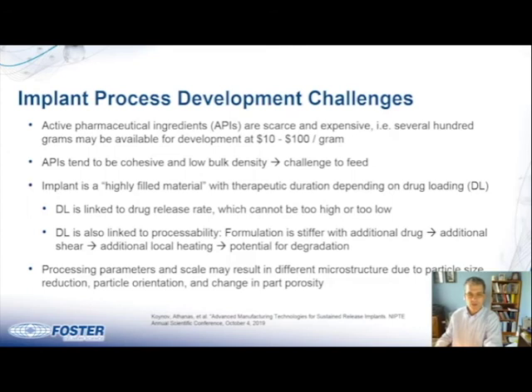The processing parameters and scale may result in different microstructure due to particle size reduction, particle orientation, and change in part porosity. These are all things that happen in both the single and the twin screw process. As I mentioned, twin screws are excellent mixers, and they do so by imparting shear onto the formulation, and that shear can really result in a particle size reduction.